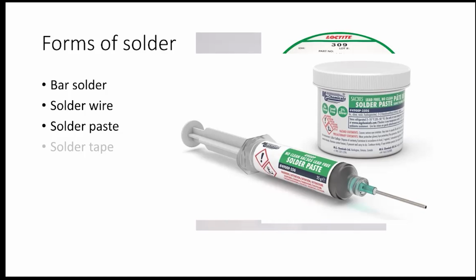I have found that if I just leave it lying about the bench, it dries out. And when it dries out, what I do is I put a little squirt of flux in it and mix it about with a lollipop stick, and it comes back into what it was before. So refrigeration is technically necessary. They'll probably not guarantee your work if you haven't refrigerated it. But I've got stuff there that's 10 years old, and I still just put a little squirt of flux in it and use a lollipop stick to mix it back up into a soft paste and then use it.